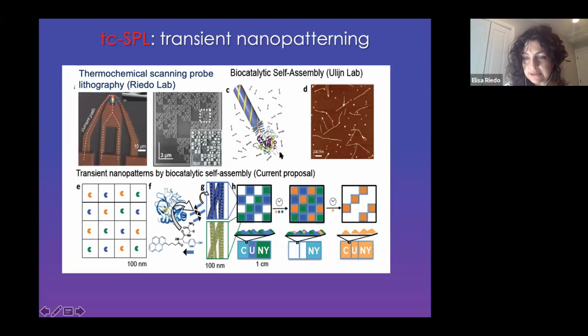So what is biocatalytic self-assembly? Essentially, this is a reaction that is triggered by an enzyme. Once certain peptides are embedded in a solution in the presence of particular enzymes, you have a self-assembly of the peptides to form this very interesting fiber structure. And not only can these fibers form, but you can also use a biofuel to stop the reaction and then to reactivate the reaction, so with an external chemical trigger.